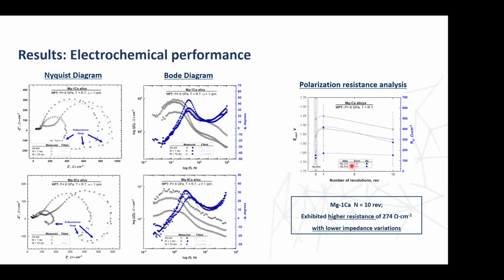In terms of impedance, also electrochemical impedance spectroscopy, we calculated especially the polarization resistance, which is the highest in magnesium 1 calcium 10 turns, which is associated with higher corrosion resistance, and it's consistent with the voltammetry. And in general, if you see this Nyquist plot, the larger the size of this loop, the higher the corrosion resistance, measured in terms of the resistance of the film that's between the material and the electrolyte. And the same can be said for the Bode diagram, and it's a way to measure the corrosion resistance.